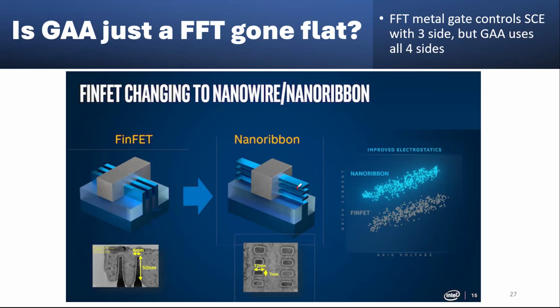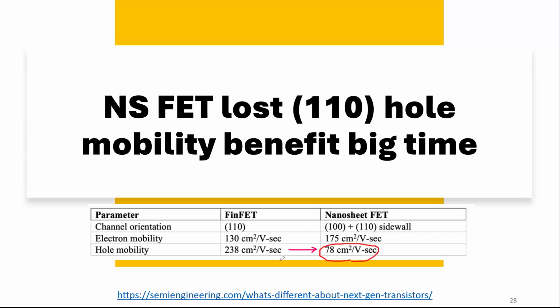Make it flat. So wait a minute, I have a vertical one here. That 110, can I do that? Yes, you can, but it's nowhere compared with this one, right? So you look at the data. Their hole mobility drops 3x. 238 to, say, 80; 240 to 80. So close to a 3x reduction in terms of hole mobility. Electron mobility gets better because you are lying flat. And 110 is not that good for electrons because the DIT is higher. And here, you need to mitigate it. You need to compensate for that. You lost big time in your mobility. You need to figure out a way to do something.